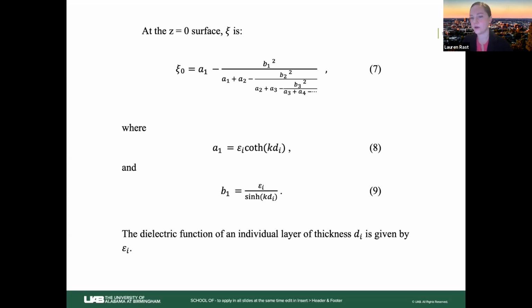People are more able to use DFT for the entire layered structure, but modeling the continuum, so bulk properties of structures that have these really small nanoscale features, is still kind of a challenge. So that's why we would want an algorithm like this, possibly for materials by design. But for our 2D materials, that's what I used. I used density functional theory to model the optical properties and to find the dielectric function for the individual layers.